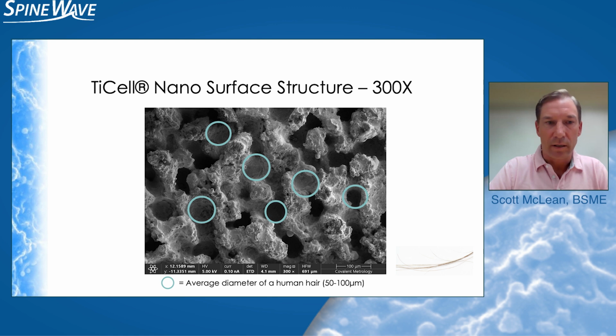Now, if you compare this to an osteoclastic pit, you'll notice right away that the pits and pores that are produced are much, much deeper than the osteoclastic pits. And that's by design. We did that intentionally so that we could have that nice tactile rough surface. It's those deep pores and those protrusions associated with them that create that surface. So given the hydrophilicity of the surface and the ability of the surface to draw fluids and cells towards its surface, we felt that we would be able to maintain the function of the osteoclastic pit regardless of its depth.